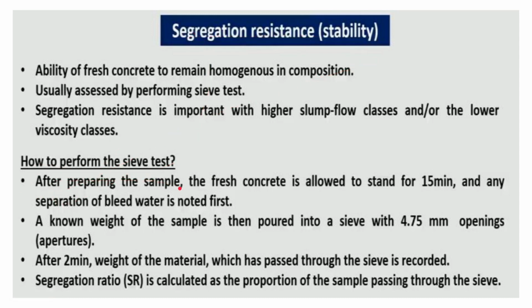After preparing the sample, the fresh concrete is allowed to stand untouched for 15 minutes, and any separation of bleed water above is noted first. A known weight of the sample is then poured into a sieve with 4.75 millimeter openings, known as apertures. After 2 minutes, the weight of the material which has passed through the sieve is recorded.